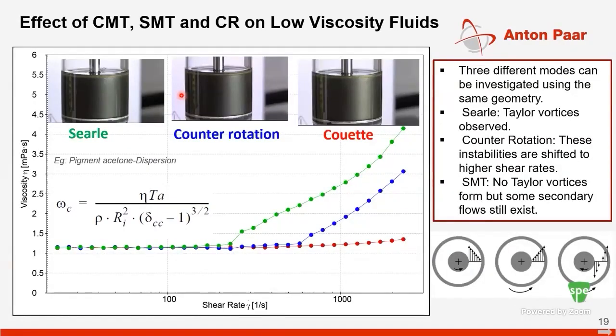Another interesting example shows the power of probing different modes on the same rheometer, this time for instabilities like Taylor vortices, which manifest at higher shear rates in a Couette type geometry. These typically happen at a critical shear rate in a concentric cylinder system. The same experiments were done in Searle mode where the bob is rotating, in counter-rotation where both upper and lower geometries move, and in Couette type flow where the outer cup moves. By incorporating these three different modes on the same device, I can extend the characterization and understand when Taylor vortices happen.